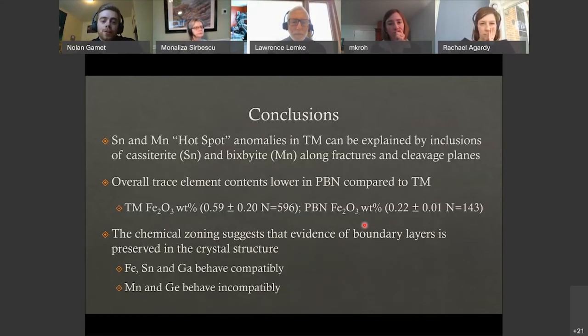For conclusions, we identified the tin and manganese hotspot anomalies, as we call them, to be explained by mineral inclusions such as cassiterite and bixbyite along fractures and cleavage planes. The overall trace contents were lower in PBN when compared to the Tin Mountain.